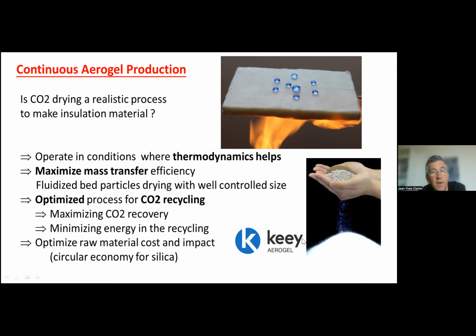insulation material. And we, again, on this industrial project, we took a quite classical chemical engineering approach to optimize thermodynamics. It's quite easy here because we just remove a solvent like ethanol, so it's quite easy to optimize this. But we have been working a lot on the optimization of the diffusion and the mass transfer using fluidized bed dryer, and working also a lot, like we explained, on the CO2 recycling loop, to minimize the energy requirement, because this is the key.